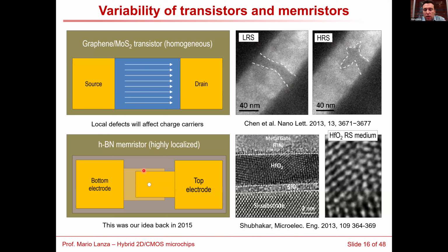So basically, if you have some wrinkles or some PMMA, which are more insulating locations, the dielectric breakdown will never take place there. So the dielectric breakdown will always take place in a completely clean location that probably also contains some local defects in the insulating material.